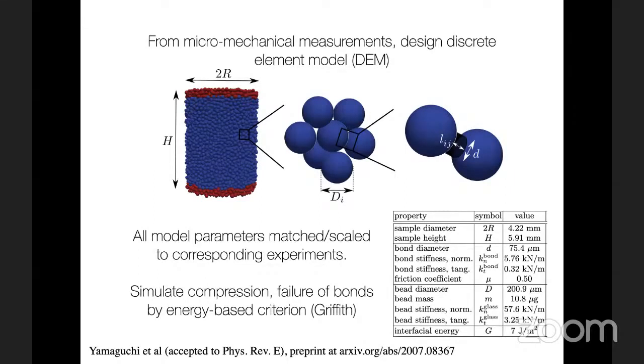And we have a failure criterion where a bridge will fail, which is based on an energy-based criterion, or Griffith criterion, where we know the adhesion energy or interfacial energy corresponding with peeling those beads apart from each other. That comes from our fracture toughness measurements. So in this model, basically every component of the model, including in some cases the particle positions, because we have X-ray tomogram data, is derived from a matched experiment. These results were recently accepted last week to PRE. There is a preprint on the archive as well of that material.